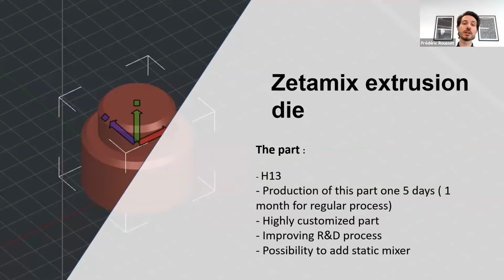So if you want to have very quick dies, it is better to do it in 3D printing to have them highly customized, because you can change the angle of the cone, the diameter, or the length of the die. This can improve the R&D process because you can do it quite quickly, and you can have the possibility to add a static mixer as well in the extruder.